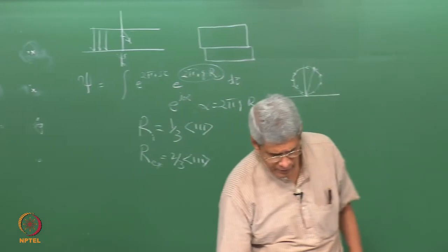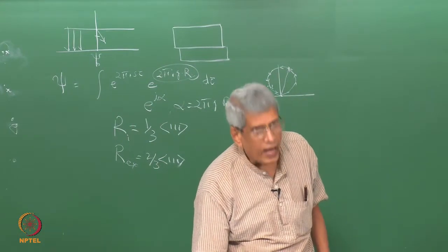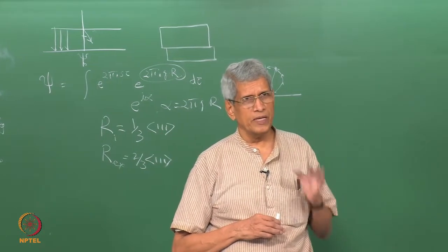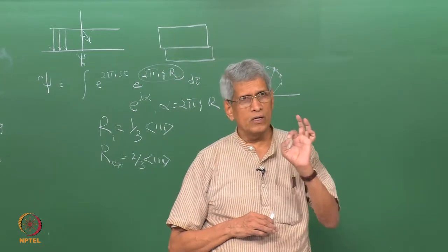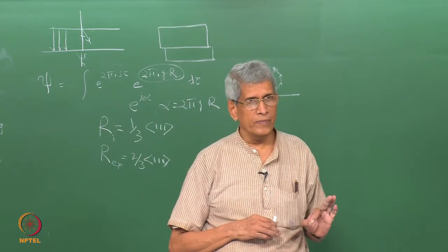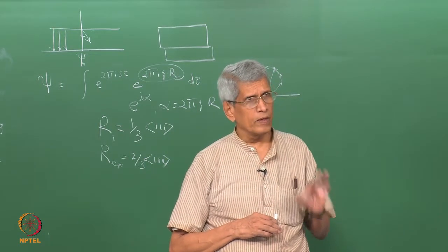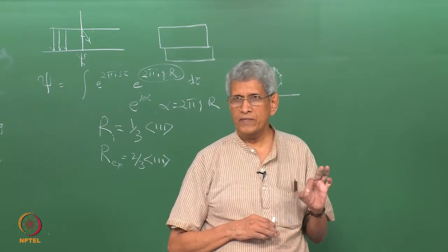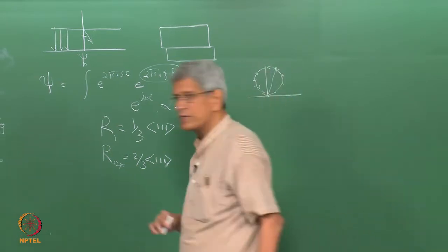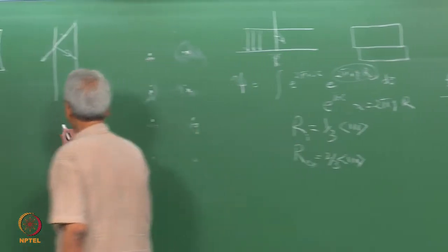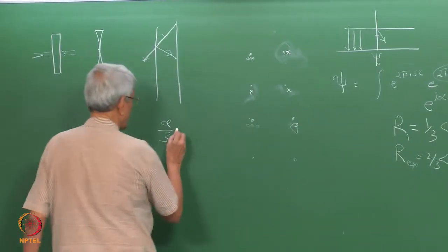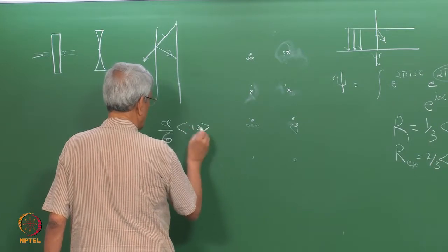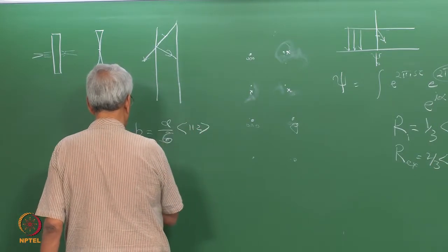Okay, and these intrinsic and extrinsic stacking faults could be created by a Frank dislocation, or they could be created by Shockley partials, correct? When Shockley partials create it, the Burgers vector of the dislocation is going to be a/6 <112> type.